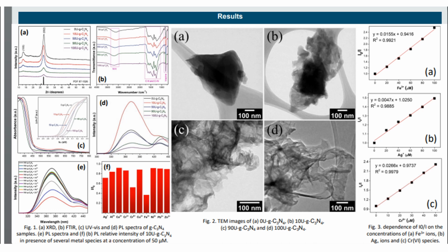The sample synthesized with melamine as a precursor shows an irregular morphology based on bulk material. Similarly, the 10% urea sample exhibits irregular shapes, characteristic of a bulk graphitic carbon nitride prepared by calcination of melamine. Instead, a clear exfoliation of the layered material can be appreciated in the 90% urea and 100% urea samples. These morphologies are in good agreement with the discussed results of XRD and FTIR analyses.